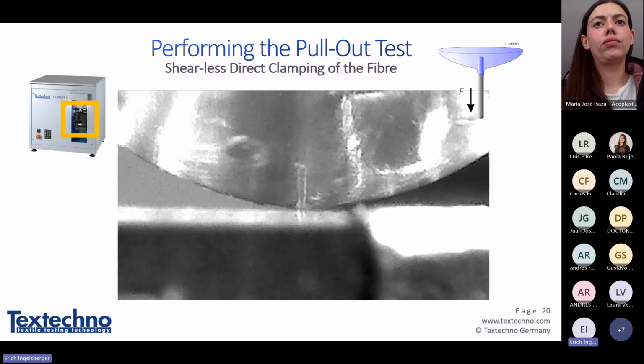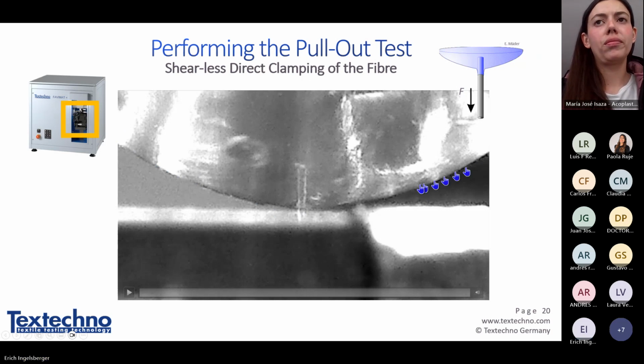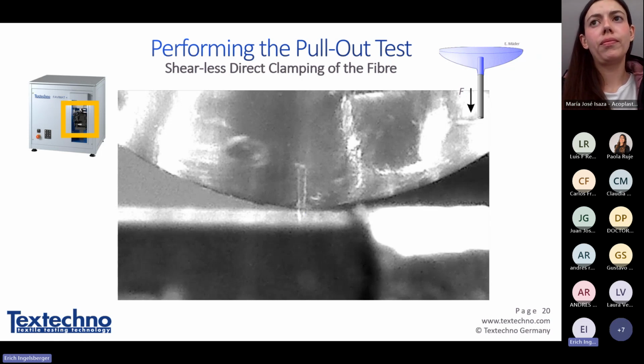The next video shows impressively what happens during this pull-out process. Here you can see the matrix drop. It is a transparent polypropylene. And here you see the fiber which is embedded into the matrix. Certainly during preparation of the test specimen, you define the embedding speed, how fast it is embedded into the matrix, and you define the embedding length. This is the length here.